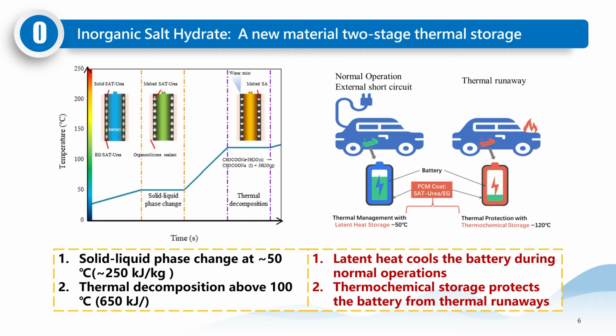We want to introduce the inorganic salt hydrate with two-stage thermal storage. So we explain what is two-stage thermal storage. In the first stage, the salt hydrate could have a solid to liquid phase change as the other PCMs do. In this stage, it melts at a temperature about 50 degrees C, with the melting enthalpy about 250 kilojoules per kilogram.